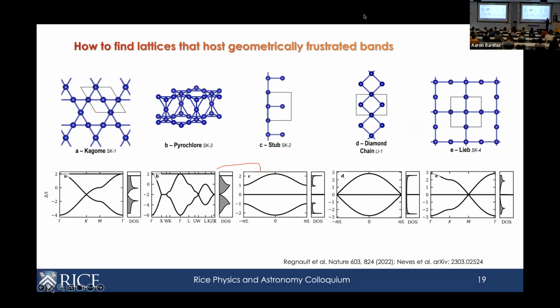This is an example. There are two papers that have come out that have gone through all the crystals that are available and looked at what are the most commonly occurring crystal lattice motifs that will give you this kind of geometrically frustrated flat bands. So these are the top 5 contenders. You have the Kagome lattice, pyrochlore, and so on and so forth. You can see each of them, the band structure, you have a flat band in all of them, right? So this is basically where we can find candidates for such kind of flat bands.